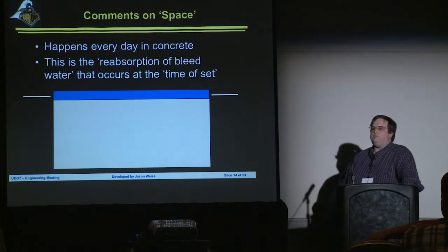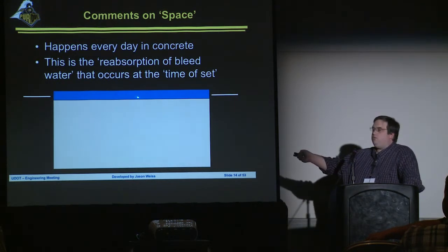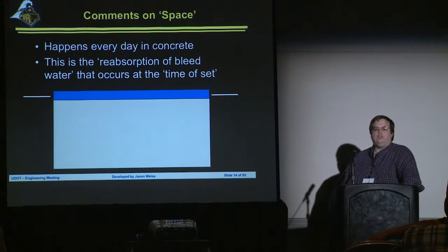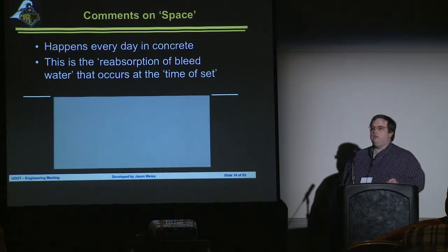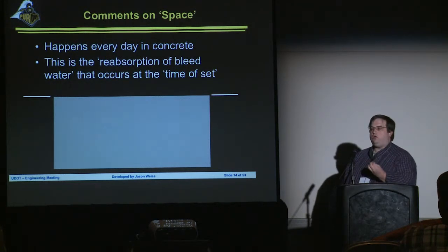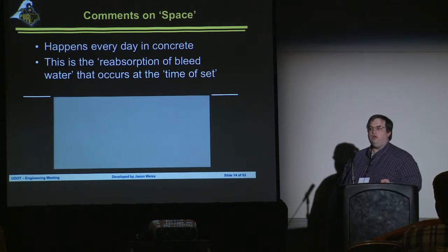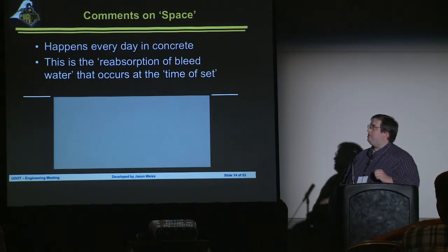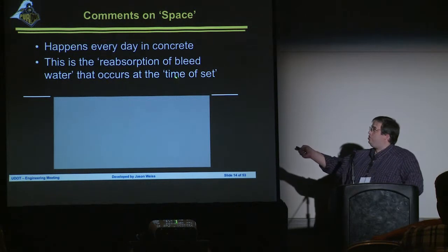Once this bleed water disappears, I was always taught as a kid growing up, you had time to smoke just one cigarette and get back out there and start finishing off the surface. Right? Why is this bleed water going away? Well, as your concrete sets, those vapor-filled spaces would rather pull water in from the outside than to leave that water sitting on the surface. So at the time of setting, that bleed water, that sheen goes away because the capillary stresses pull that water back into the system.